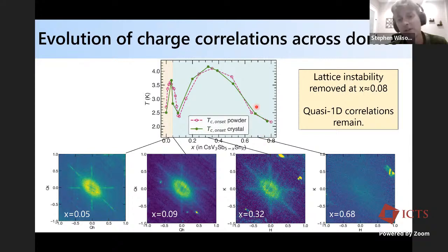And then you can go all the way to where superconductivity vanishes. So in this regime, this is just a partial volume fraction superconductor. The charge correlations completely vanish. So they seem to vanish at the same point with superconductivity, and they undergo this evolution from the 2 by 2 correlations into what in our model is a quasi one-dimensional charge correlation volume.